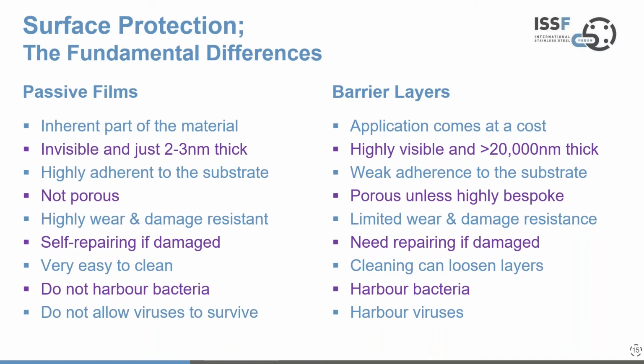By contrast, barrier layers, you have to spend money to put them on in the first place. They're visible and thick. They have weaker adherence to the substrate material. They tend to be porous unless they're highly bespoke. They offer limited wear and damage resistance. They need repairing if damaged, because from a hygiene perspective, it opens you up to all sorts of challenges. Cleaning itself, if it's reasonably aggressive, can loosen those layers, and they're known to harbor both bacteria and viruses.